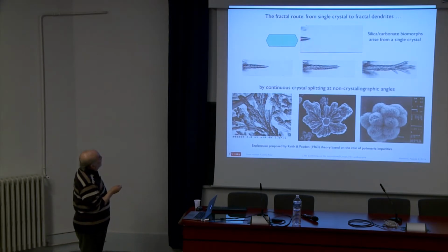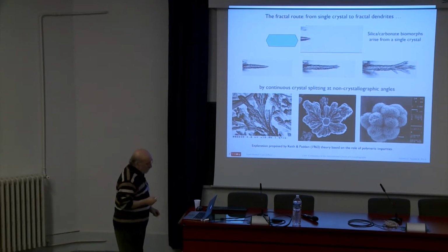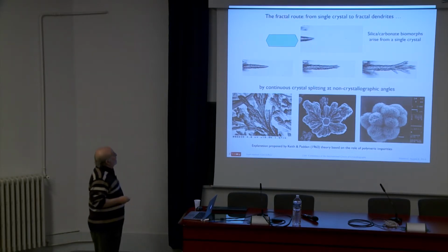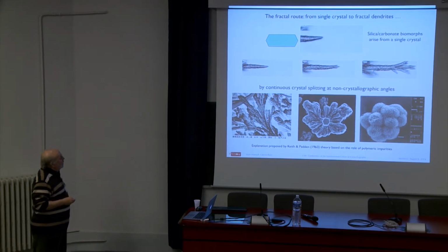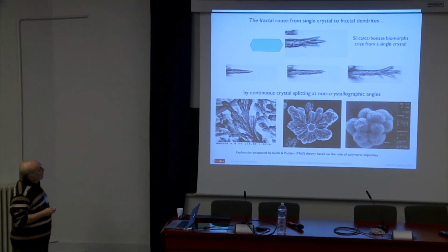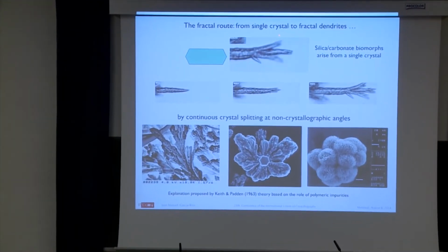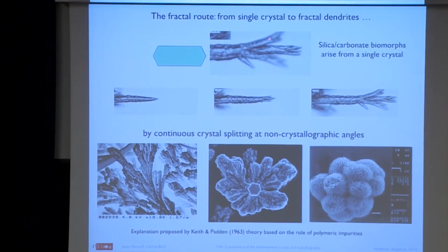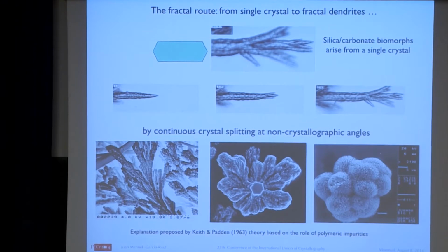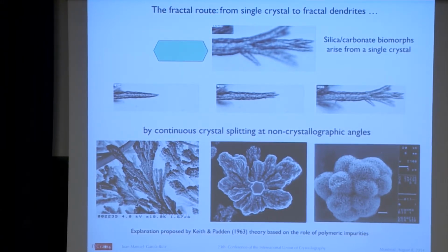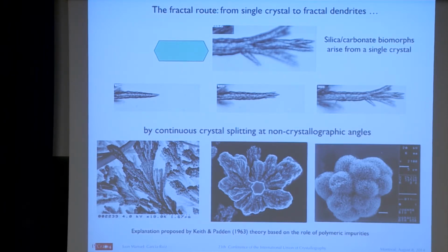you have the single crystal growing here, okay? So this is the case of barium carbonate. You have not only the prismatic phase, but also the bipyramidal phase. This bipyramidal phase is growing, and you will see what happens is that the crystal growth, because of the impurity of the silica, produces the branching, the splitting of the tip of the crystal, and you have a branching which is non-crystallographic branching. It's not like a snow crystal, you know, in which you have branching at identical angles. Okay, here there is a different kind of angle.